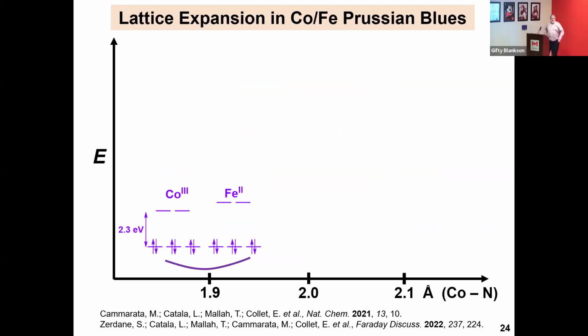All right, so to show you the mechanism that's been proposed, all fine and good if it's just chemistry, but you need to understand the why. That's the most important part. This was formed by Talal Mallah in France and other coworkers. And they found that at low temperature, a technique called X-ray magnetic circular dichroism, and XANES and EXAFS. For those who are interested, I can talk about later, but time considerations, not now.